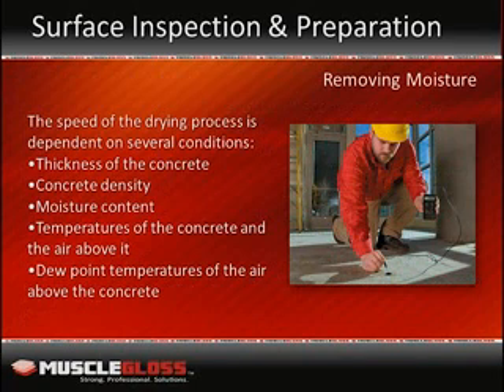The following are some general rules when dealing with moisture. The speed of the drying process is dependent on several conditions. Thickness of the concrete. Thicker slabs dry more slowly. Concrete density. Dense concrete will dry more slowly. Moisture content. More water content requires more time to dry. Temperatures of the concrete and the air above it. Dew point temperatures of the air above the concrete. Low dew points will cause migration of the water from the concrete.